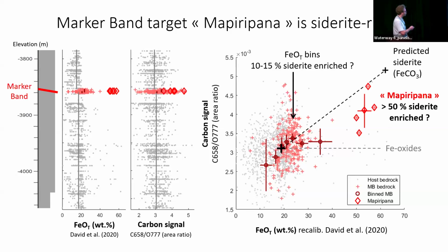You see iron as a function of elevation, and this is the carbon signal. That's the very noisy signal. And when you put both together, you see really the marker band stands out compared to the host stratigraphy in terms of iron, as expected from APXS. But here, there is a slight trend in the bulk marker band data, positive carbon and iron. This is barely statistically significant, unfortunately, but there is one target we're going to talk about a lot in this talk, which is